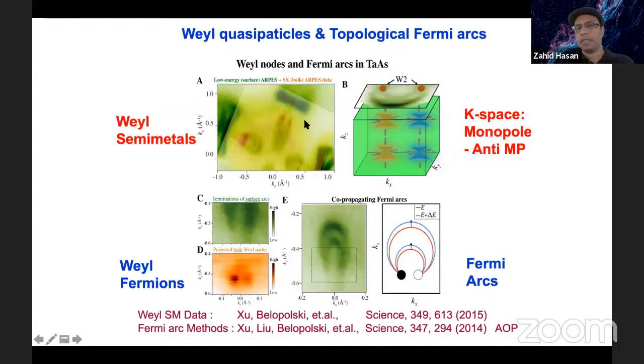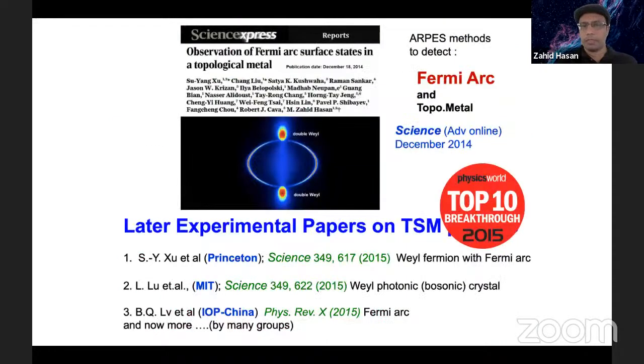So then we can also put the bulk ARPES measured with high photon energy and surface ARPES with low photon energy. When we do the bulk ARPES, we find two dots. When we do surface, we find arc-like states. And what is interesting is that these arcs terminate at the bulk Fermi surface, or bulk dot states. So this is bulk-boundary correspondence. These arcs terminate at the Weyl nodes. So this was our theory-independent proof, without comparing with band structure calculation or anything. Experimental proof of Weyl and Fermi arc states.